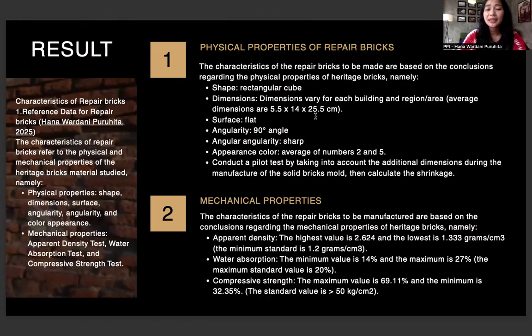The characteristic of the repair bricks to be manufactured are based on the conclusion regarding the mechanical properties of heritage bricks, namely apparent density. The highest value is 2,624 and the lowest is 1,333 grams per centimeter cubic. The minimum standard is 1.2 grams.